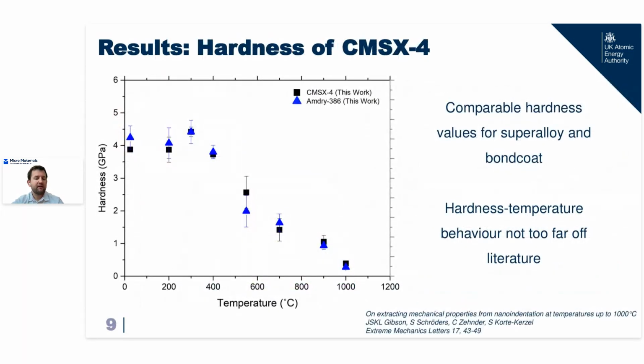So then by making a very thin sample, a few hundred microns thick, and testing very quickly so we didn't ruin our indenter, we managed to get these data points for our superalloy, which we can use as a reference here in black, as well as the bond coat that we care about. We see that we get comparable mechanical properties for our superalloy and our bond coat over all ranges of temperatures, which was very nice. It means we shouldn't be developing any thermal stresses. And we see the hardness temperature behavior is pretty close to literature.